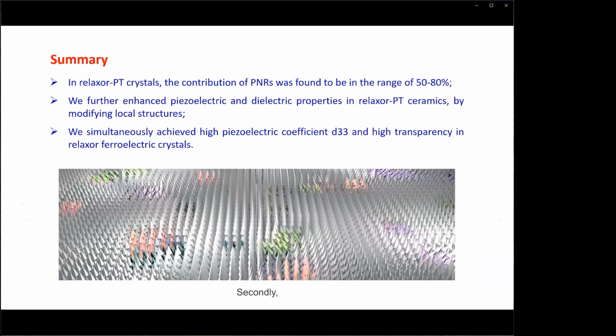Secondly, we further enhanced the piezoelectric and dielectric properties in Relaxor-PT ceramics and crystals by modifying the local polar regions. Finally, by domain structure engineering, we achieved both high piezoelectric coefficient and high light transparency in Relaxor ferroelectric crystals. These crystals may benefit many applications in the near future, for example, photoacoustic imaging transducers and transparent actuators for haptic-related applications.